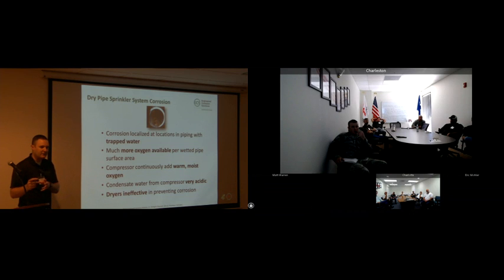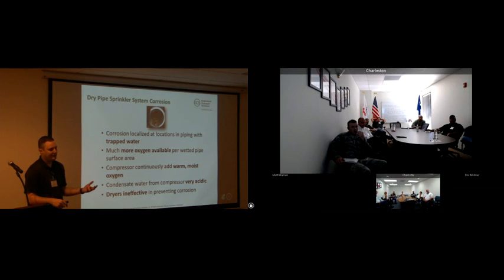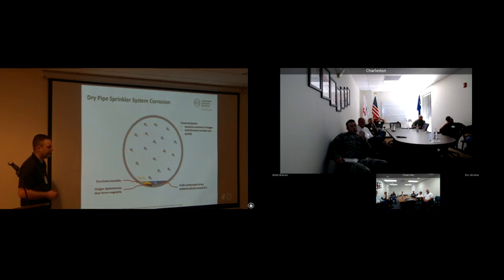We have much more oxygen available, like we said, almost an infinite amount because we have a compressor consistently putting in more oxygen as the pressure drops in the system. That oxygen that's being added most of the time is going to be warm and moist. It's going to have some condensate in it. We might have desiccant dryers, we might have dry air packed systems or regenerative air coolers, but most of the time those systems are not necessarily maintained the way they should be, and we're still putting in some level of moisture. But all of that aside, remember that when you do your trip test, you're putting in enough moisture that's going to stay in the system to cause all the corrosion you're ever going to need to have a leak.